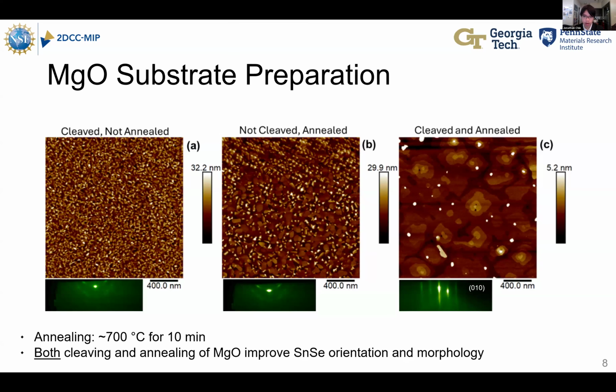When we do both of these steps, we find that this is what allows us to access this nice, smooth morphology where we have a predominant in-plane orientation. We have these individual layers, these grains growing on top of each other, and each one has a step height of one layer, so that half unit cell. Some next steps are to try to isolate this, where instead of nucleating these additional grains on top of the underlying grain, if we can grow just that underlying film without the excess, that would allow us to establish that layer control.